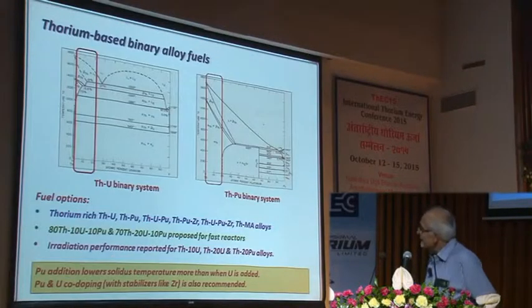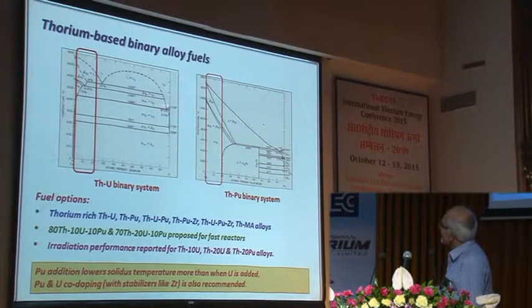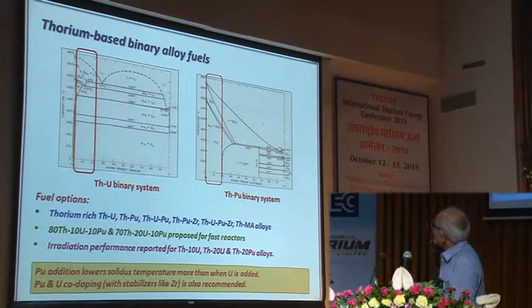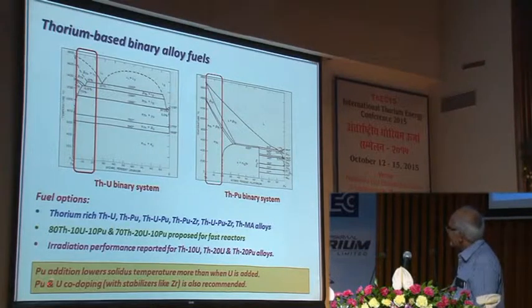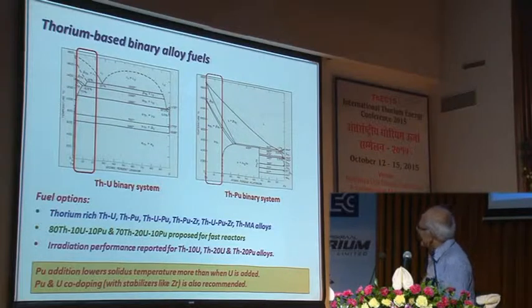So what we have started looking at, before that, just look at these phase diagrams, and you can see here, if you take the uranium-thorium binary system or uranium-plutonium binary system up to, let's say, 20% uranium, you can see the solidus temperature is in the range of 1400 degrees centigrade. So that's a very positive thing, except that Pu addition lowers the solidus temperature more than when uranium is added. And the fuel options are thorium-rich uranium, thorium, plutonium, and so on. You can have the ternary alloy.